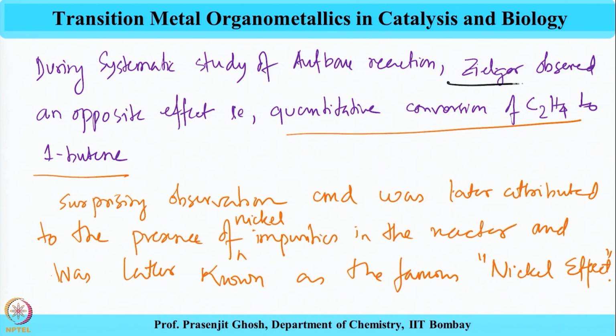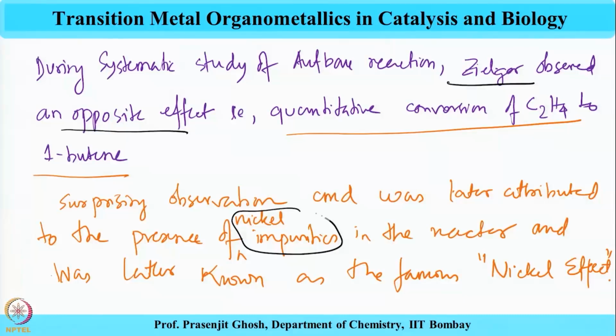While pursuing this Aufbau reaction under different conditions, carrying out a systematic study, Professor Karl Ziegler observed that in certain cases exactly the opposite was happening, that is, a quantitative conversion of ethylene, instead of making polymer, was making 1-butene, and this was a contrasting and surprising observation at the time of the study, where the focus of the Aufbau reaction was to make long chain polymer, and here they were quantitatively getting the dimer. So, this surprising observation was later attributed to the presence of impurities in the reactor, particularly nickel impurities, which later came to be known as the famous nickel effect, that actually triggered the discovery of Ziegler-Natta polymerization. So, with this I come to an end of today's lecture.